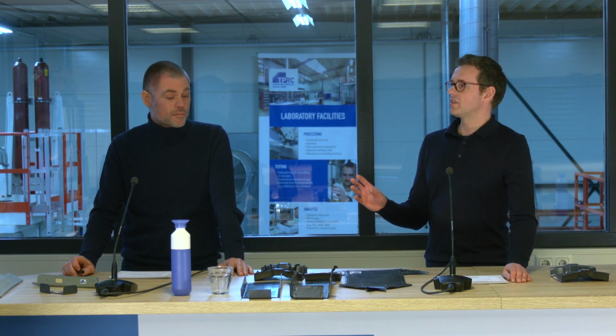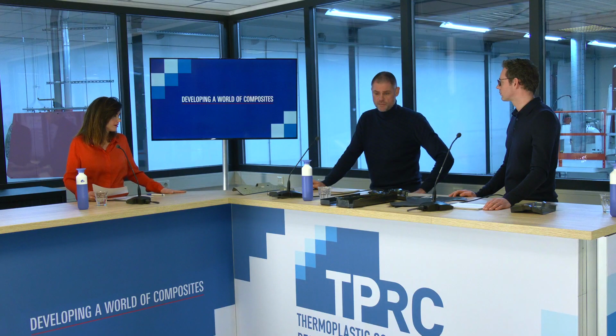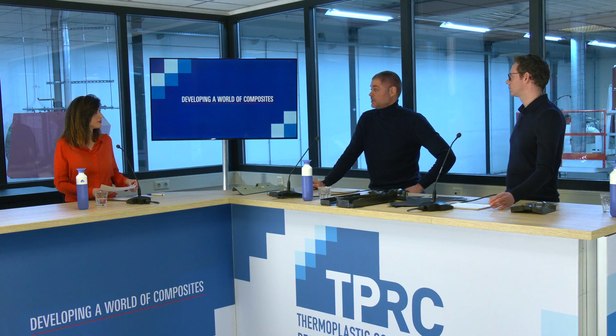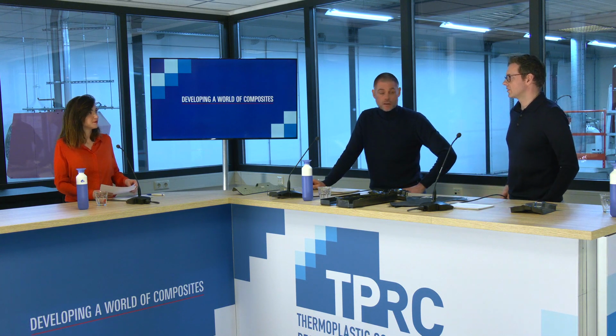And that range there, the material's in its molten stage, and when it's molten, it's soft, and you can form it. You need to stay within that window and take care of the cooling down. Form it before it has cooled down too much, of course. Some basic numbers: say up to 50 degrees above the melting temperature. And then tool temperature between melting temperature and glass temperature. There are some guidelines here. And it's material specific, especially. So not a simple answer. No, it's okay. Sometimes that's just it.